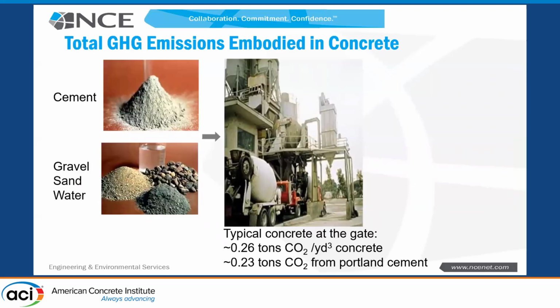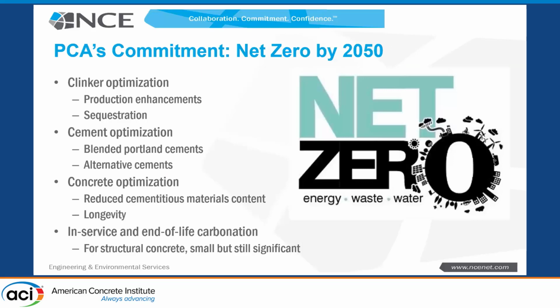When we look at typical concrete at the gate, the number here is about 0.26 tons of CO2 per cubic yard. That's kind of an average number. It can be higher or lower. And roughly 0.23 tons of that is from the Portland cement in that concrete. So guess where the focal point is? If you're going to deal with this problem, what are you dealing with? Portland cement, right? And how many cement manufacturers do I have here? Are these numbers about right? Now, these are our numbers. And as a manufacturer, you know this is what you've got to do.